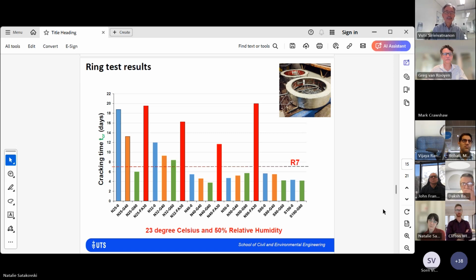I'm not going to discuss the specifics of the mix design today because we're going to run out of time. But obviously, you can see that fly ash is pretty good for delaying early age cracking, and slag is not the same at all. It's more likely to crack early, and increasing the compressive strength of the concrete is not a good thing either. All the concrete at 40, 50, and 60 MPa, except for the fly ash, are cracking. That just highlights that there's a lot of difference in performance between the different concretes we're using, and it's better to use a concrete that is likely to perform well. That's the purpose of that type of performance-based testing.